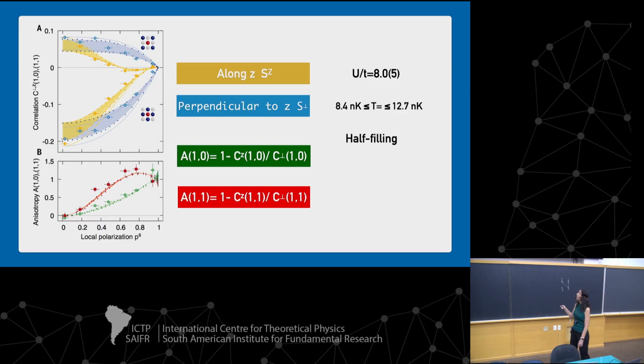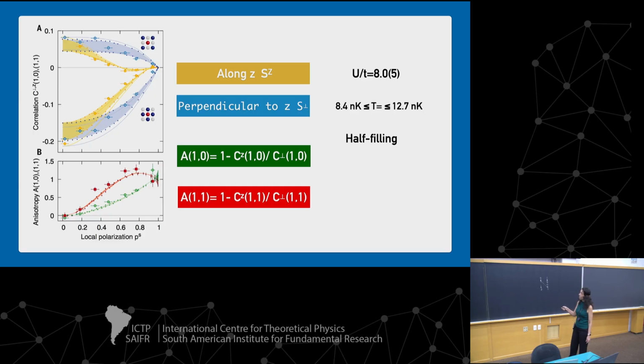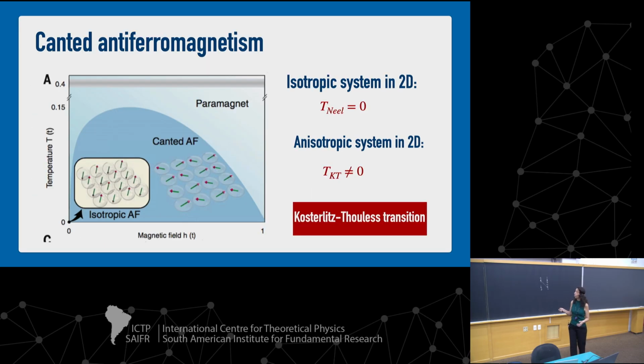And we can calculate an anisotropy factor, which is just 1 minus the correlation along the z direction divided by the one perpendicular to the z direction. And this here, the near neighbor is negative. And the next near neighbor is here, which is the very same thing here. So in the down part, the negative part, we have the next near neighbor, and in the upper part, which is positive, the next near neighbor along the diagonal. And here is the same. And the anisotropy we see is different if we look at the first neighbors or the second near neighbors. So what happens is, clearly, the magnetization is not isotropic. It's only isotropic here.